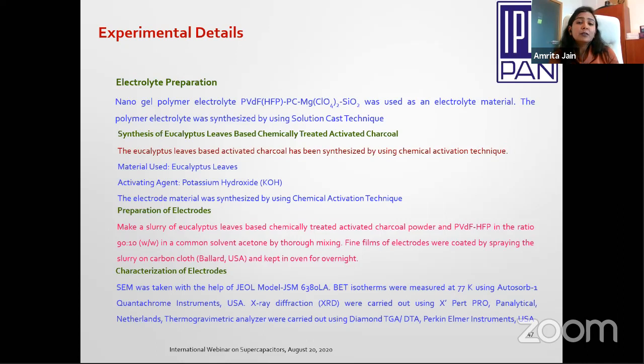For synthesis of activated carbon, charcoal from eucalyptus leaves, we have used chemical activation, and I have used potassium hydroxide as an activating agent. The electrode material was synthesized using the chemical activation technique. The electrodes were prepared by taking carbon cloth as a substrate material. So this device was completely flexible in nature, because this was a fabric and you can actually bend this device like this. Characterization of the electrodes was carried out using standard methods like SEM, scanning electron microscopy, and BET surface area analysis. Surface area analysis was used to determine the surface area of the synthesized electrode materials.